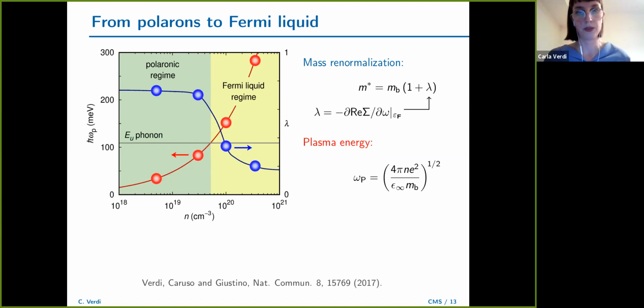I see, right. Another question is, you mentioned several times that you do this at the DFT level, or do you treat the electrons differently? No, we don't do GW. We could, but we don't. One of the reasons is that there are calculations, for example on the band structure of TiO2, where it's shown that GW is mainly a rigid shift of the bands. There are materials where GW can also change a lot the effective mass from DFT. But first of all, it's not what we wanted to focus on, and second, we saw that doing GW would have been mainly a rigid shift in this case. Okay, thank you. No problem.